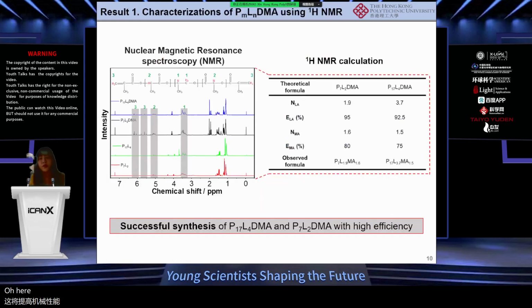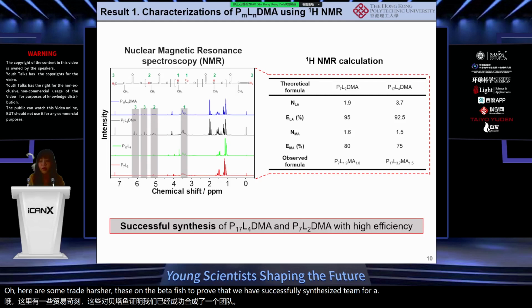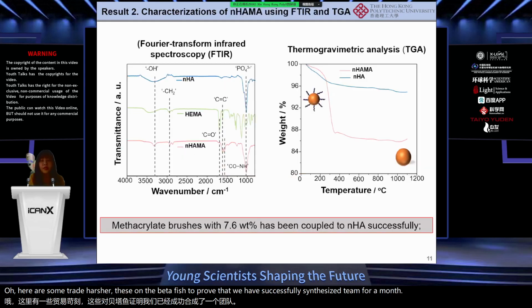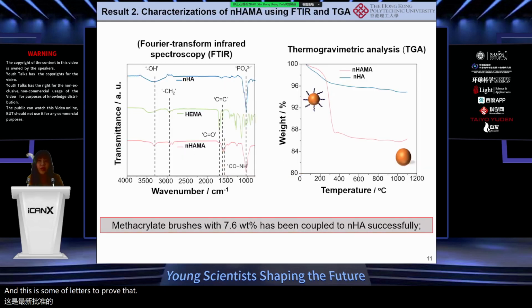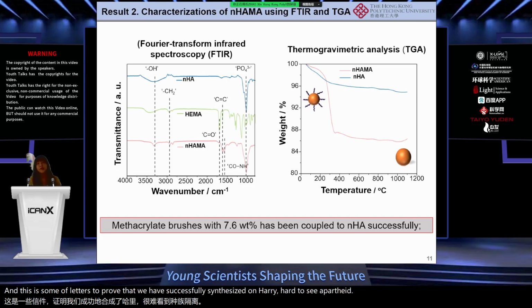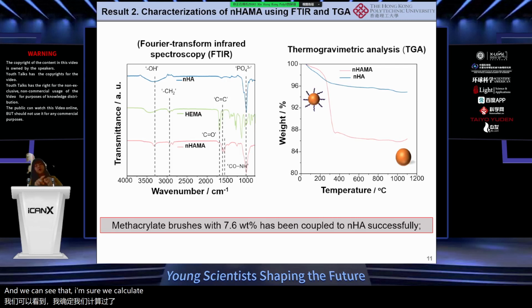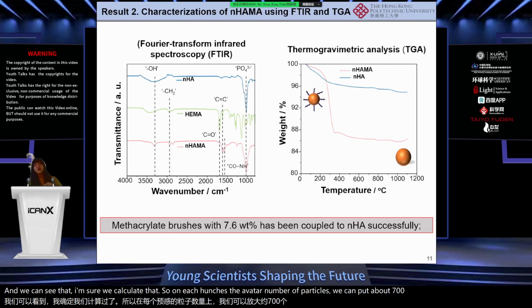Here are just some data. These are the data to prove that we have successfully synthesized the polymer. And this is some data to prove that we have successfully synthesized the hairy hydroxyapatite. We calculate that on each hydroxyapatite nanoparticle, we can put about 700 to 800 hairs.